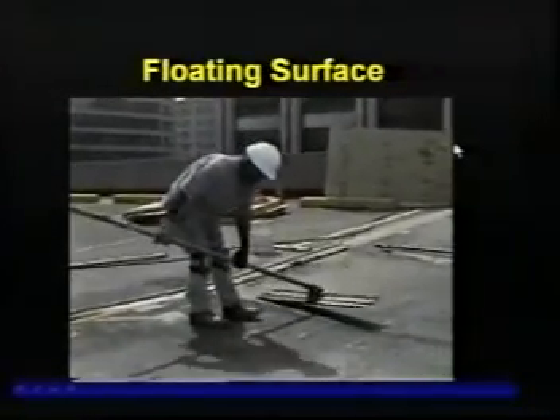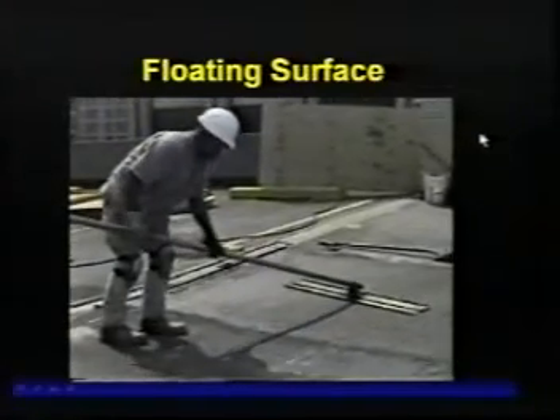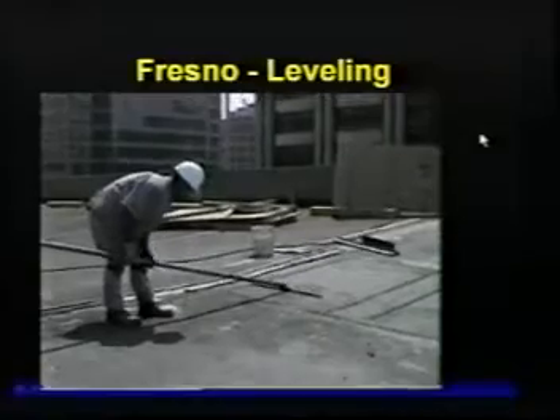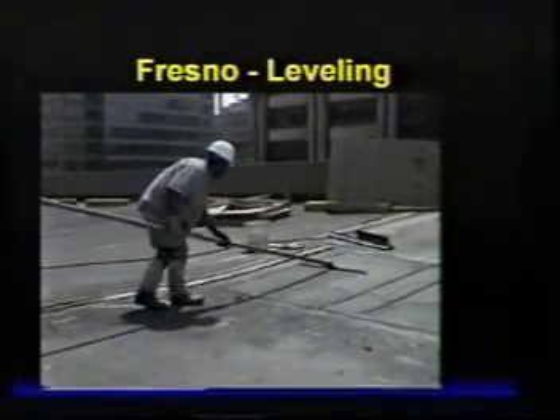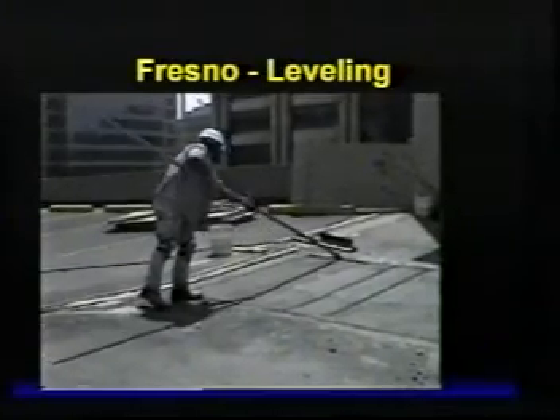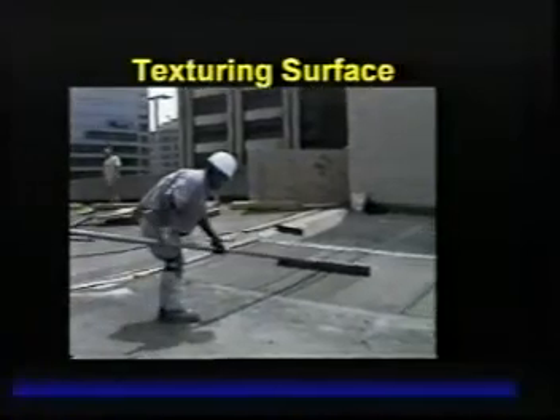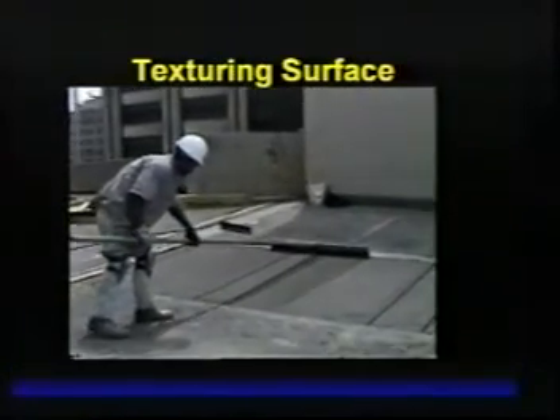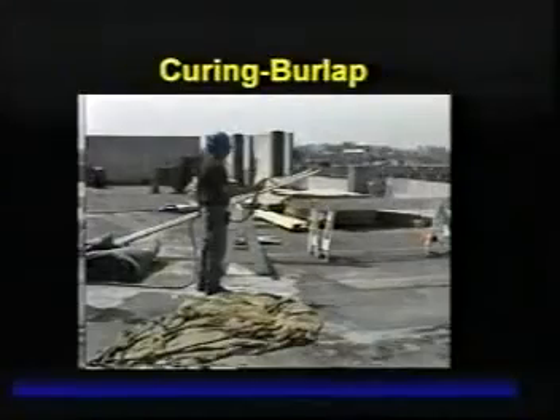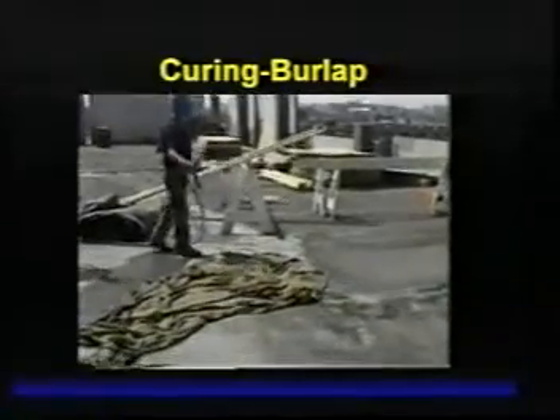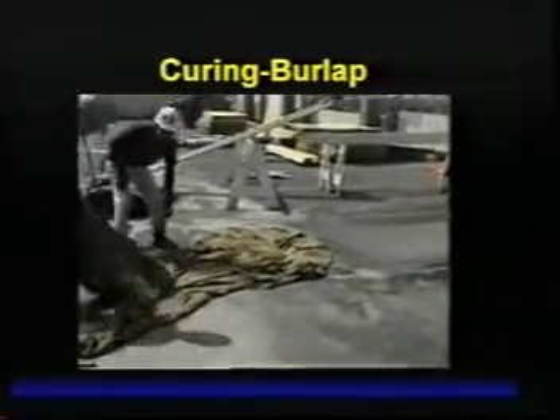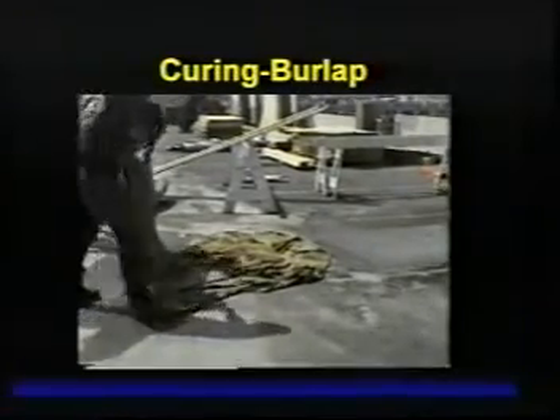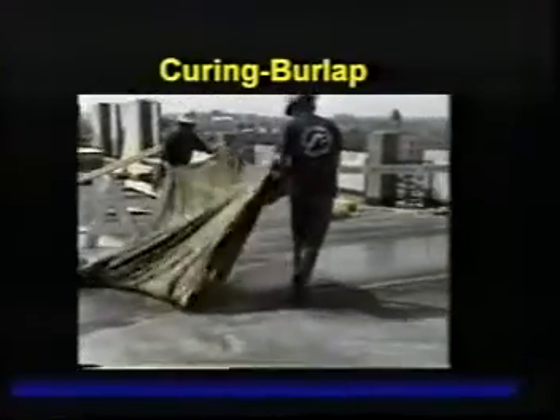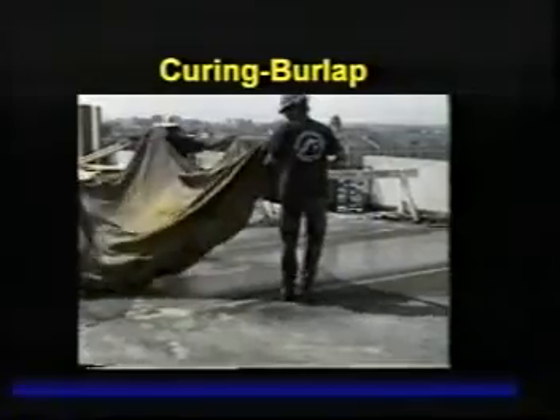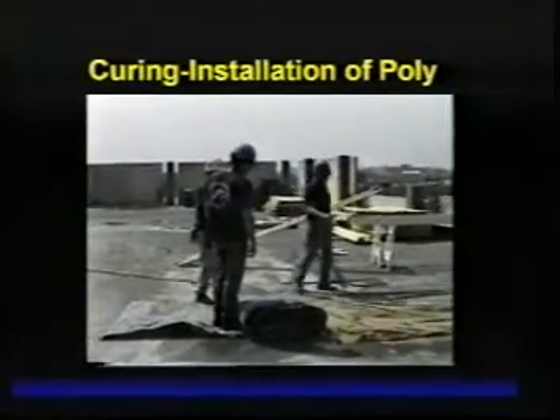Again, we're following exactly the same procedures as new construction. We're going to float the surface, followed by, in this particular case, a Fresno, which does a little bit more leveling, knocks the bumps out. Again, this step can be eliminated in a lot of applications. And then some texturing. Again, texturing is not always required. In this particular job, the broom finish. And then there's a curing process. And curing can be either a membrane curing or a traditional wet curing. In this particular case, they're using burlap, which is important to keep there, obviously, for the specified duration, 3 to 7 days, depending on the specification, and followed in this particular case with some polyethylene to protect that.